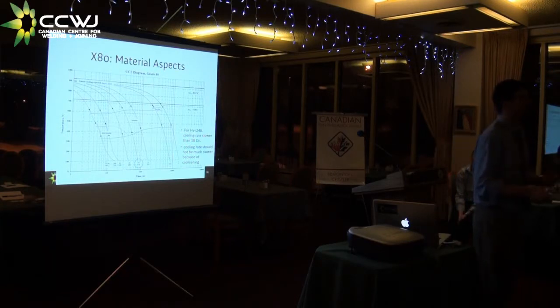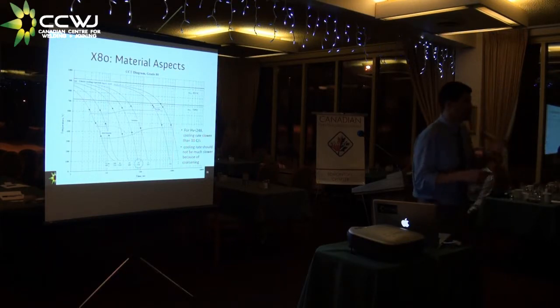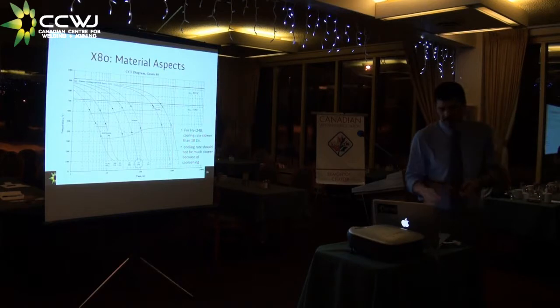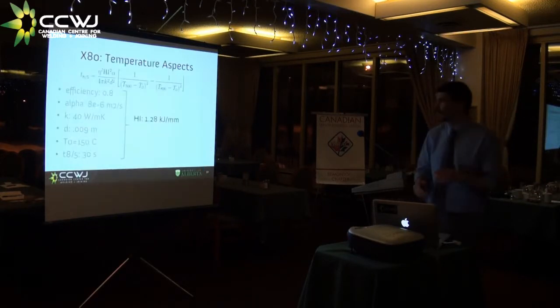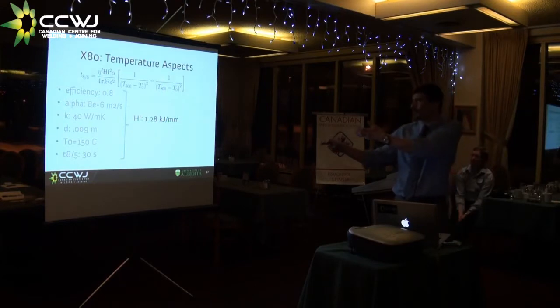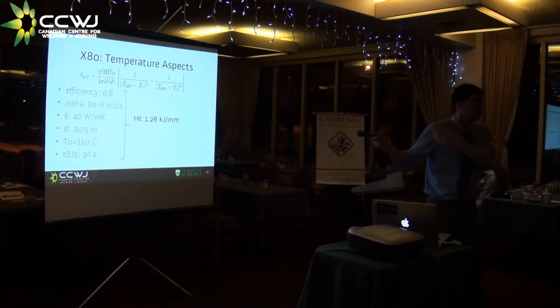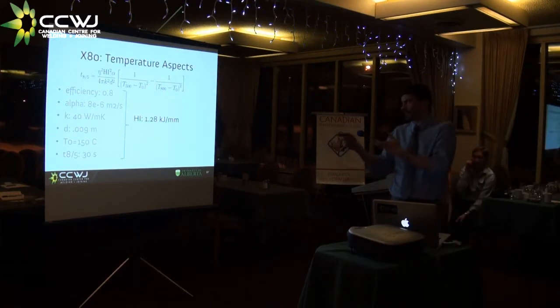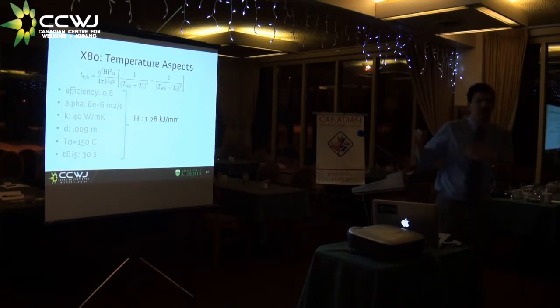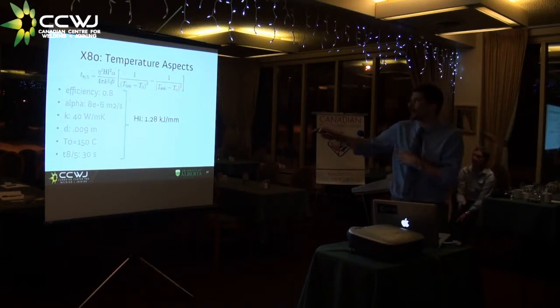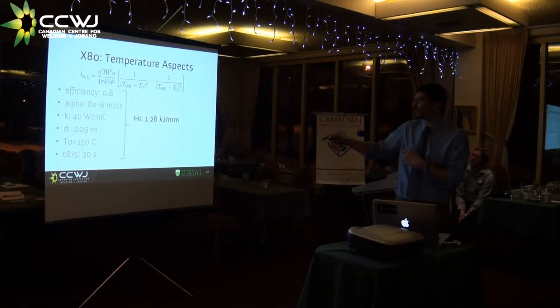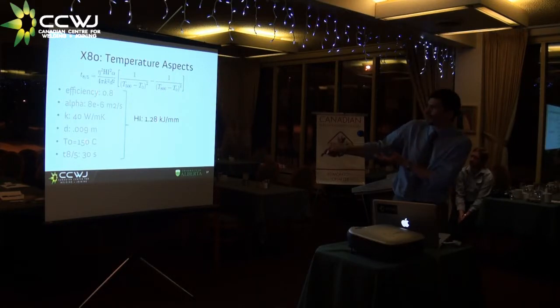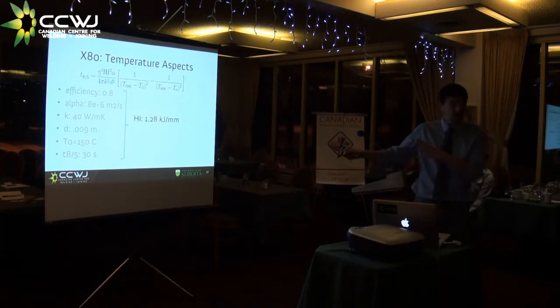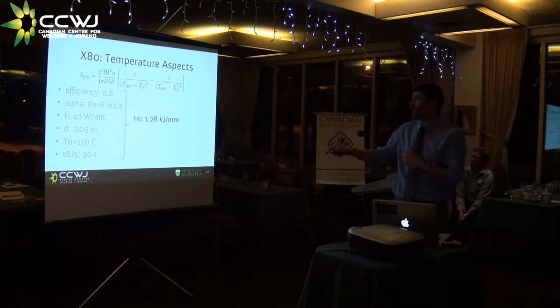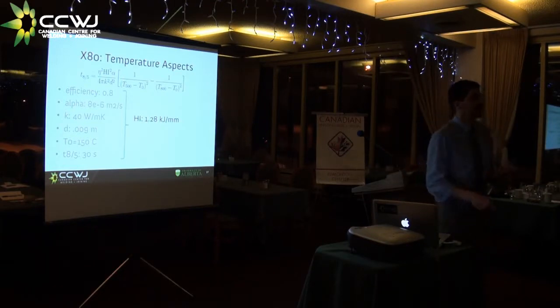All right, so now you don't want to go much slower because you're going to have a coarse microstructure, and that's not good. So let's aim for 10 degrees per second. And so we would go to our formula here, and for T85 typically is thin plate. I'm skipping the confirmation. And we have a formula, and it says, for the tabulated values that I put in the previous slide, these are the same tabulated values, you should have a heat input of 1.28 kilojoules per millimeter.